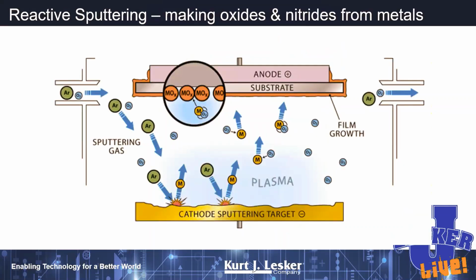Keep in mind that your deposition rates for things like metals are typically much higher than what you get from oxides or nitrides, so if you want high deposition rates and you also want to make, let's say, an oxide coating, you can do what's called reactive sputtering. So I can sputter from, let's say, a titanium metal target or an aluminum metal target. I can introduce my argon process gas, but also add some oxygen into that gas stream, so that I'm going to have my argon ions collide with the target, eject metal atoms or molecules there, but then they're going to collide with the oxygen that's in the system, and we'll do a little bit of chemistry, and by the time we get to our substrate here, we're actually depositing an oxide.